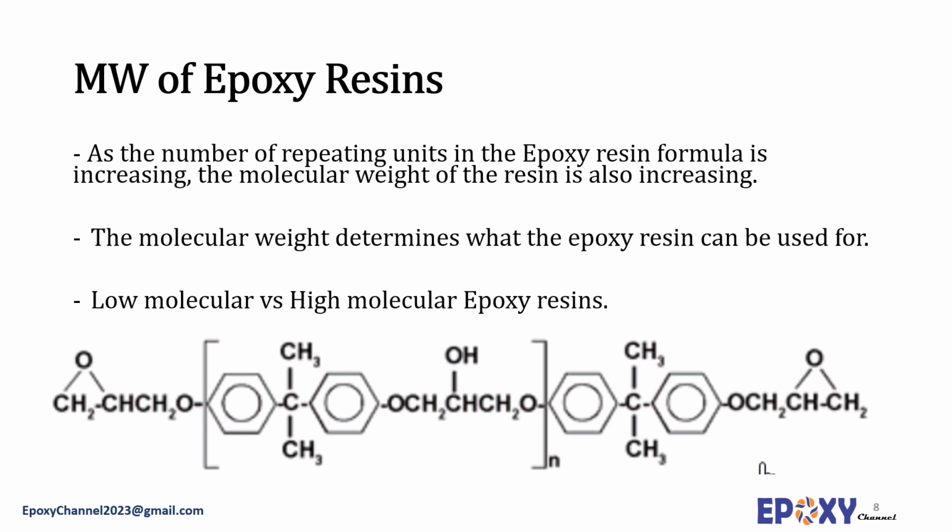Epoxy resin with a mean molecular weight of over 700 is called high molecular, and epoxy resin with a mean molecular weight of under 700 is considered low molecular. The low molecular can be handled without solvent additives, which evaporate, and are therefore used for casting, tank coatings, gap fillings, glues, etc. And the high molecular epoxy resins must, as a rule, be dissolved in organic solvent to be manageable, which limits usage to paints and lacquers.